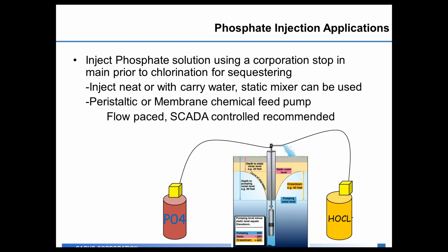Typically, phosphates are fed with a peristaltic or a membrane chemical feed pump. Ideally, you'd love to have the pump flow-paced and SCADA controlled so that you can make adjustments to it remotely. In the case of groundwaters, a lot of times pumps are tied into the power for the well pump, and the pump kicks on when the well kicks on, so you're only applying phosphate when the well is pumping. Like I said earlier, you want to keep in mind that you inject first if you're sequestering, so the phosphate needs to go prior to your chlorination.